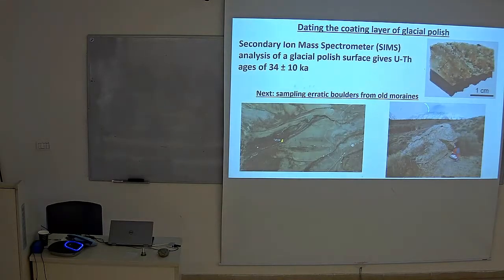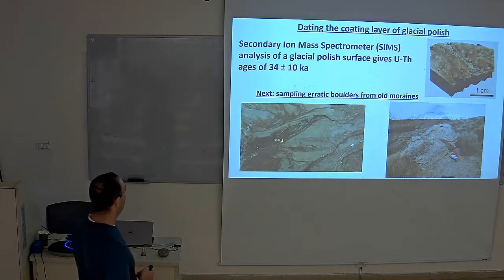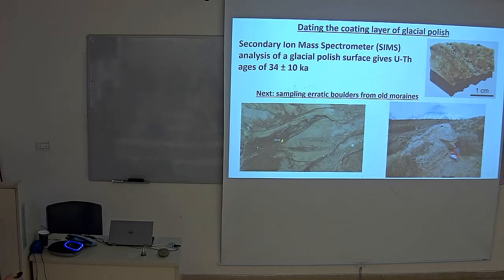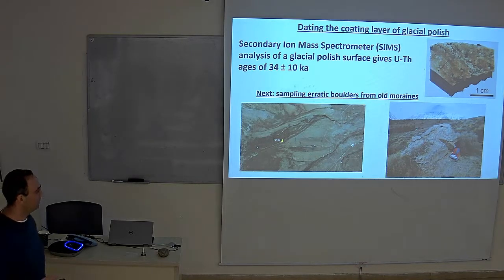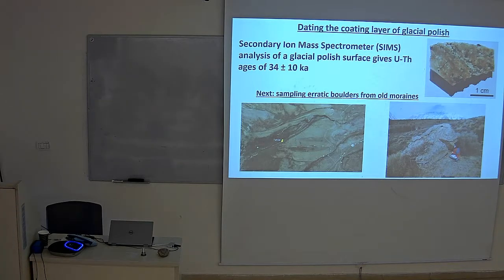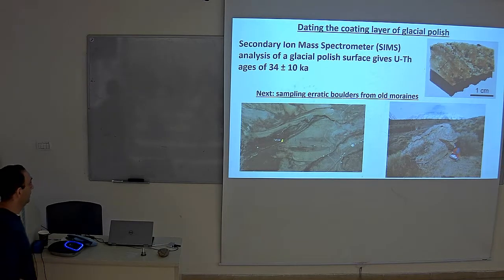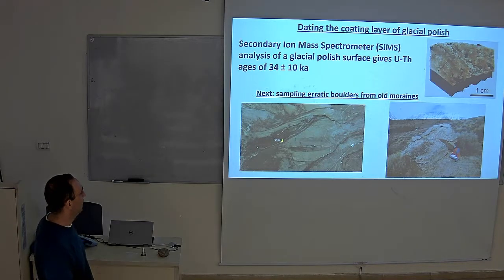So we tried with the SIMS, the secondary ion mass spectrometer at Stanford, and what we get is an age of 34,000 plus or minus 10. For me it was a huge error. It was hard to believe, but what was important is that it's out of equilibrium, and while the rocks formed about 90 million years ago, this is giving a totally different, measurable age, and we can give an age for this part. So this is what we measure.